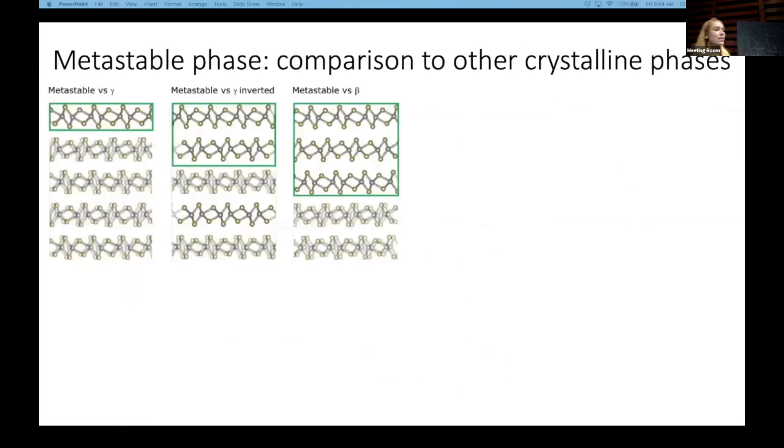So there are two intriguing coincidences that I pointed out. One is that with potassium dosing, the different terminations seem to switch. So the spectra that were initially characteristic of face A afterwards become characteristic of face B. The other coincidence is that the spectra qualitatively look an awful lot like the beta phase, which we don't claim to be actually producing because it is energetically unfavorable.